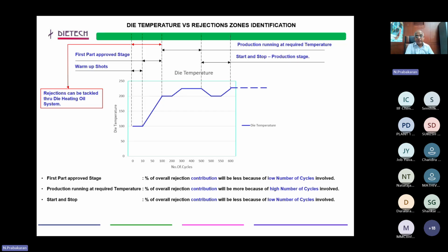Probably the die temperature is reaching from 100 to 200 degrees. That 200 degrees is what I'm giving as one reference. According to the casting configuration and other factors, it will vary. Probably I have taken 200 degrees as a reference. So after the warm-up shots, the second stage is the first part approval stage. That also takes 10 to 50 cycles.